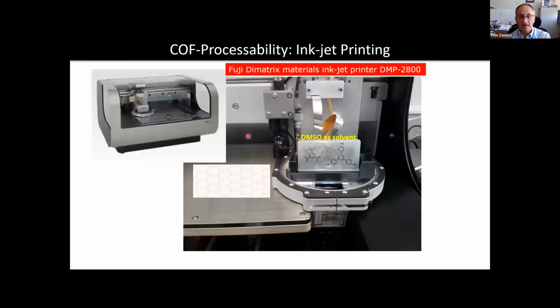Okay, and then we decided to use this reaction to do a proof of concept experiment. For that, we charged this cartridge with the two initial molecules, and we selected DMSO because it's much better as solvent for this particular experiment. And what we did is we used this Fujifilm Dimatix inkjet printer to allow us to deposit our particular ink on different substrates. This is the result that we got when we printed this ink on silicon oxide. And as you can see here, we deposit droplets of about 15 picoliters.